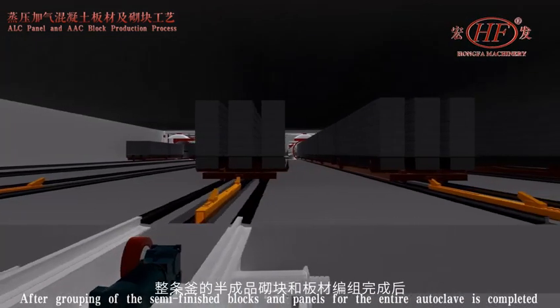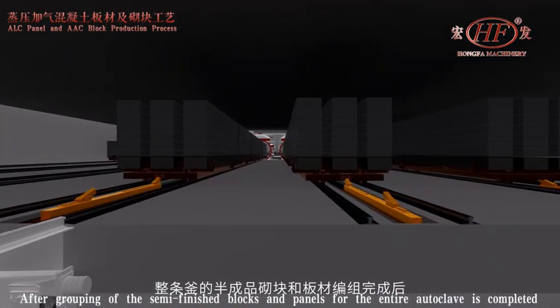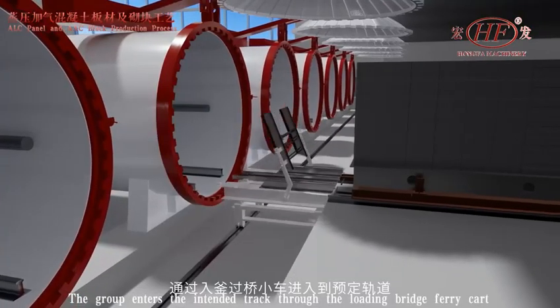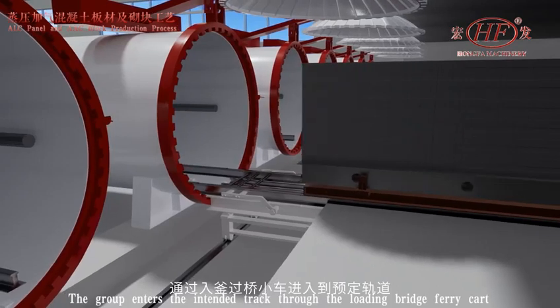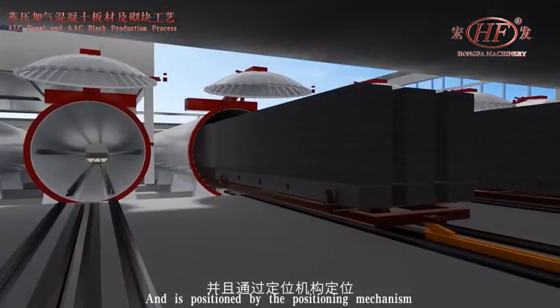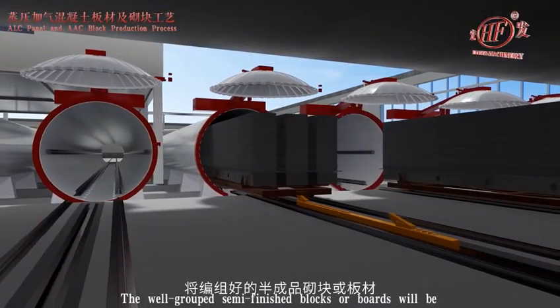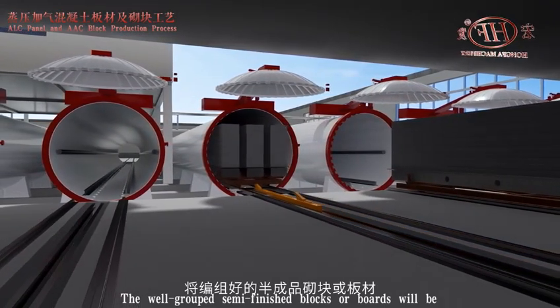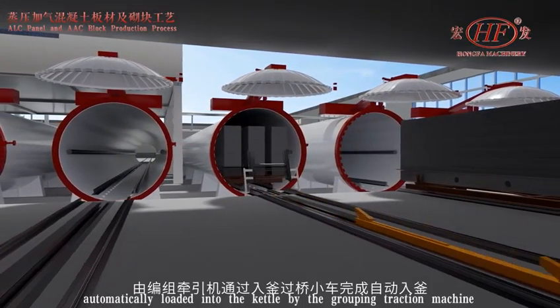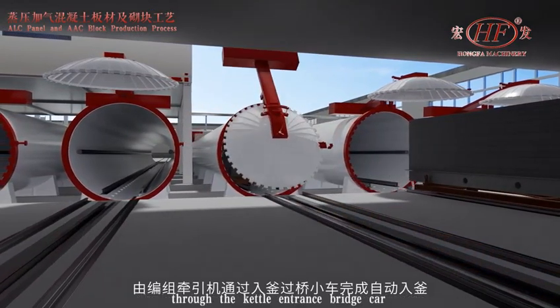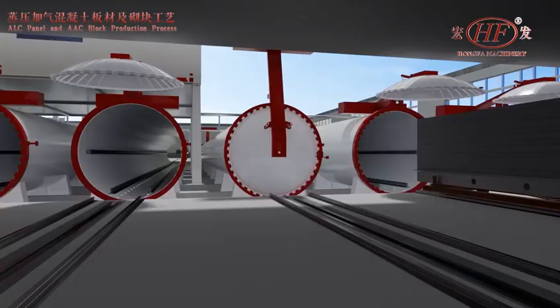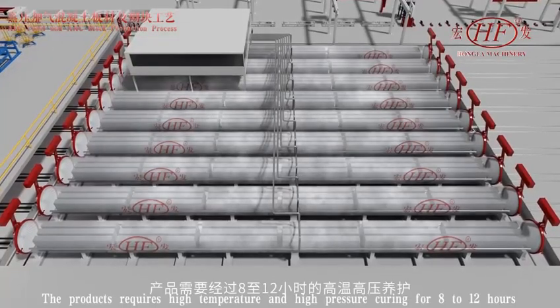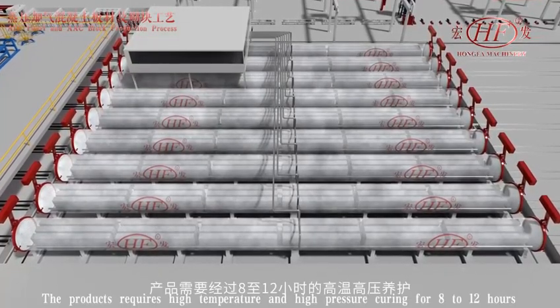After grouping of the semi-finished blocks and panels for the entire autoclave is completed, the group enters the intended track through the loading bridge ferry cart, and it is positioned by the positioning mechanism. The well-grouped semi-finished blocks or panels are automatically loaded into the autoclave by the grouping traction machine through the loading bridge ferry cart. The product requires high temperature and high pressure curing for 8 to 12 hours.